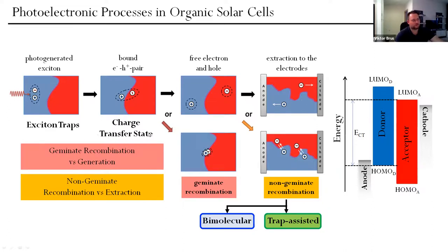There is a so-called charge transfer state formed with the energy of the effective band gap of this donor. And there is some dynamics which could result in recombination of the exciton even at the interface. So that is called geminate recombination, and these processes are quite fast. They happen on the time scale of a few nanoseconds after exciton generation. So they are really different from other types of recombination. So this is geminate recombination of excitons at the interface.